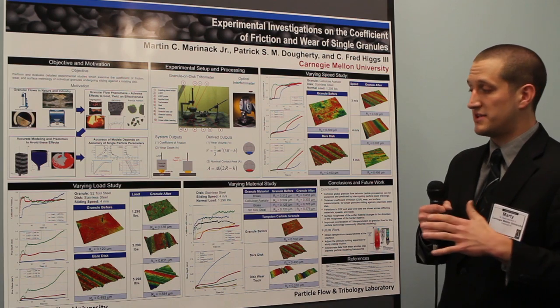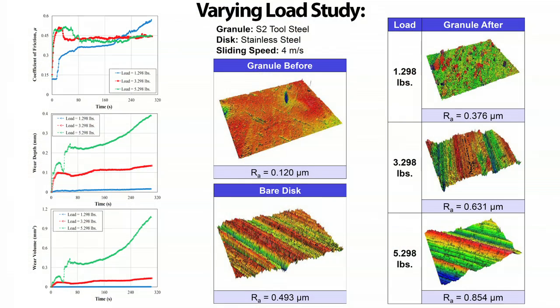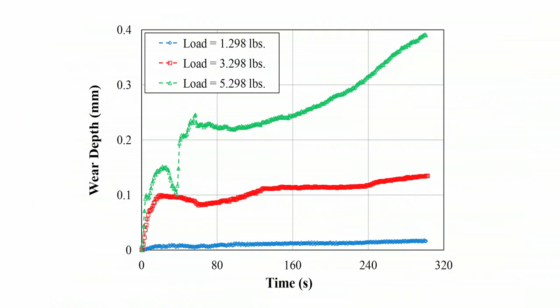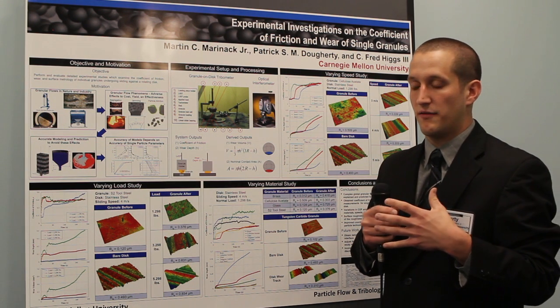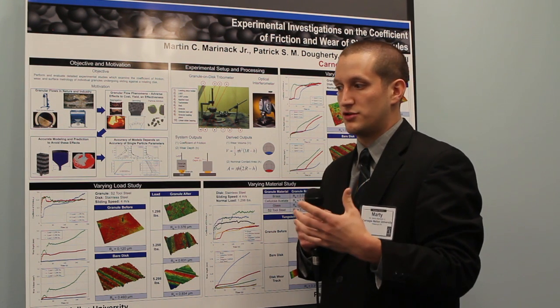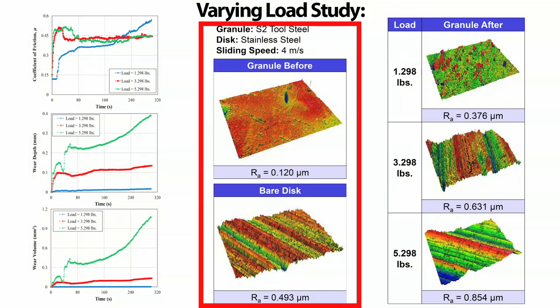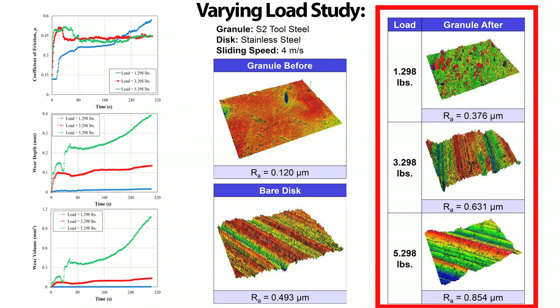So in addition to speed studies, we also ran a number of load studies. The one I display here is for a tool steel granule. What's not surprising is that when we look at the wear, the higher load naturally causes more wear of the granule. Accounting for the different amounts of wear based on load is very important for these modelers because it affects the shape change of the particles, which has been shown to have a large effect on the results they're trying to predict. So if we look at the surface shots in this instance, what we see is that we have a granule that starts out much smoother than the disc which it's sliding on. And during sliding, the granule's surface patterns actually start to look more like the disc, and the granule in turn also becomes much rougher.